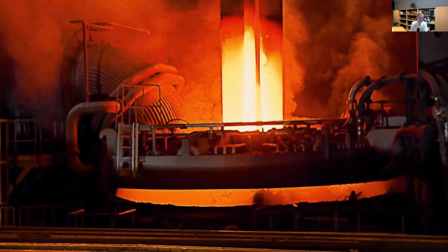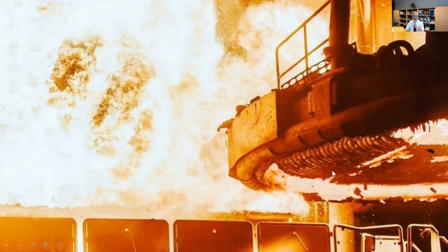We have them all over the globe, distributed among companies that specialize in making steel from scrap. As you saw in the beginning, steel does very well in scrap recycling, particularly the so-called corrosion-resistant stainless steels, the steels that you know from exhaust pipes, from your kitchen, and from all the corrosion-resistant parts in the chemical industry. These are very expensive steels. They contain elements like chromium and nickel, which you want to retrieve from the scrap. That's why this technology of melting scrap through these electrodes, through a plasma, is quite established. And it's big fun. If you ever have the possibility to get close to these ovens, it's the best experience of your life. It's kind of noisy, but it's really cool.